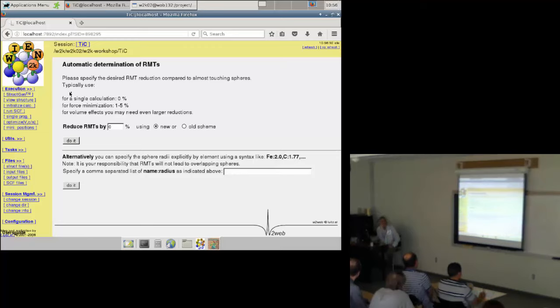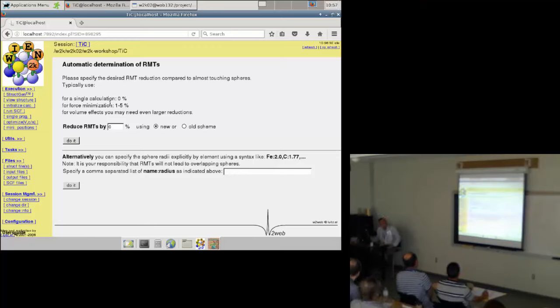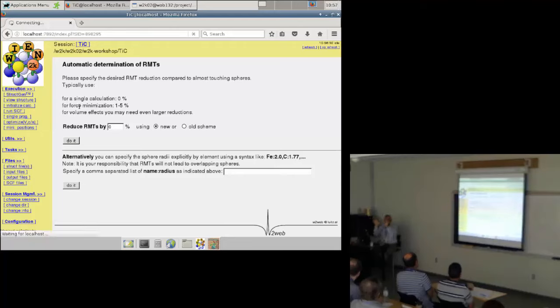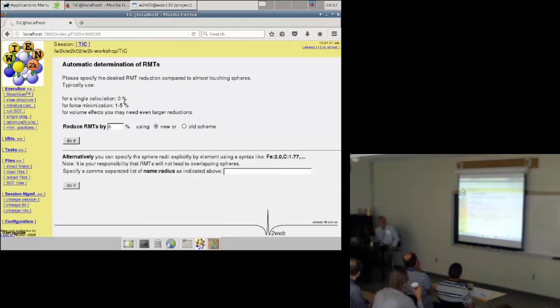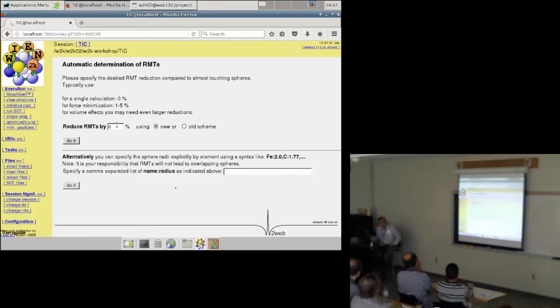If it is a single-step calculation using the experimental structure to calculate a spectrum, use zero. If you want to optimize forces — meaning the atoms are free to move — or study volume effects such as calculating the lattice parameter by computing energy versus volume to get a parabola and find the minimum, I would reduce the sphere sizes by one to five percent. For a total energy calculation, let's reduce by five percent. It doesn't matter too much.